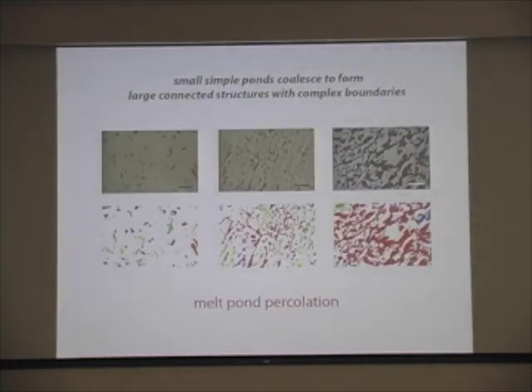We also see a percolation phenomenon on this large scale. Namely, here are individual melt ponds. They coalesce. They start to form pathways just on the scale of the image, and then they dominate the image.